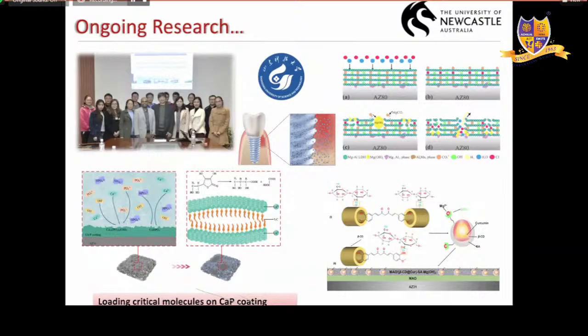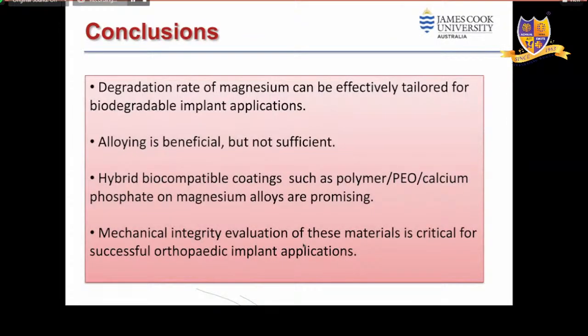I've established a collaboration with a Chinese institute, and I visited them a few years ago. We're looking at tailoring the calcium phosphate coatings by adding bio-inspired molecules, loading critical molecules for biocompatibility and antibacterial property, and adding silver nanoparticles and so on, which I'm not going to discuss right now. So, in conclusion, the degradation rate of magnesium can be effectively tailored for biodegradable implants. Alloying is beneficial but not sufficient. Hybrid coatings are essential and promising. And mechanical integrity evaluation is critical for successful implant applications.